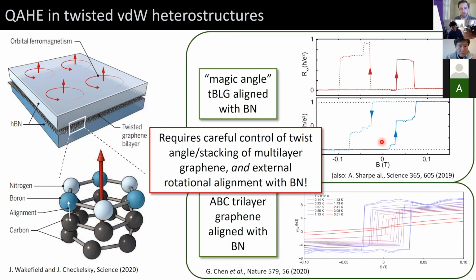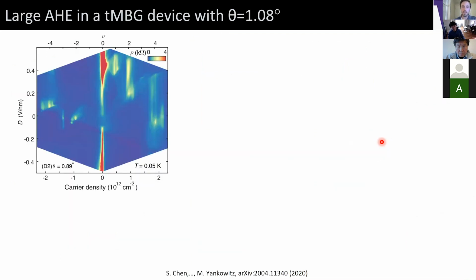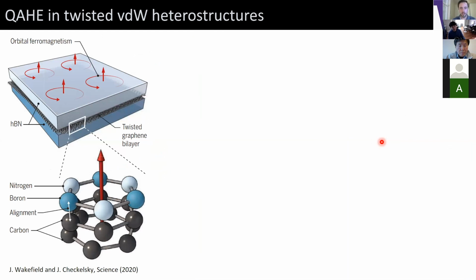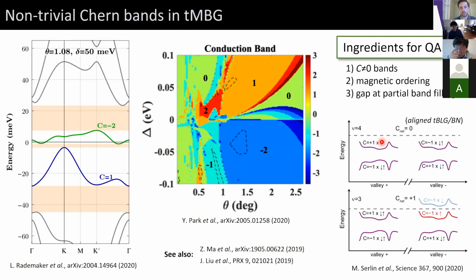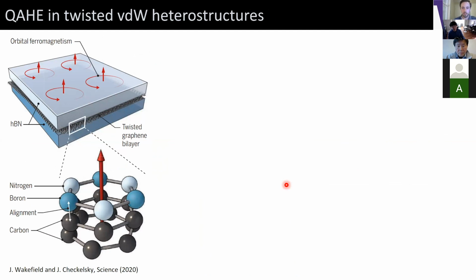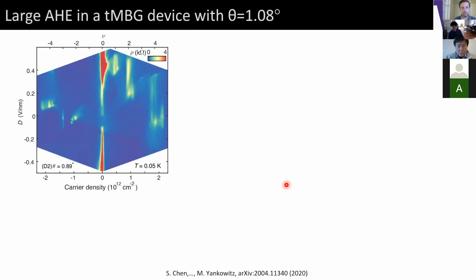So really what we would like is if there was somehow some way to do this intrinsically without having to rely on external alignment with extra crystals. So following the motivation that these twisted monolayer-bilayer systems may intrinsically satisfy this property, we looked at devices with other twist angles. And in a device that we recently measured at UW at about 0.9 degree twist angle, we see a somewhat similar phase diagram to the one that I just discussed.